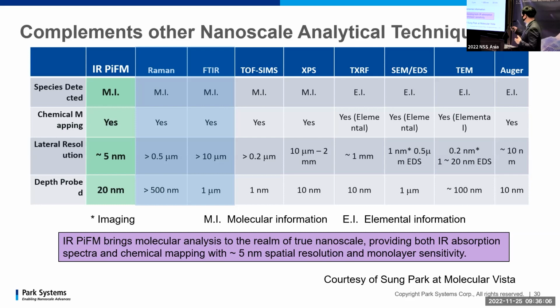When we see the technical difference between other technologies and PIFM, most of these, Raman and FTIR, detect the signals using photo detectors, but that really limits the lateral resolution because the signal is diffuse. But in PIFM, the probe itself is the detector, so the resolution depends on the fine radius of the probe. So we can easily get to 5 nanometer and less than 5 nanometer resolution for chemical identification.